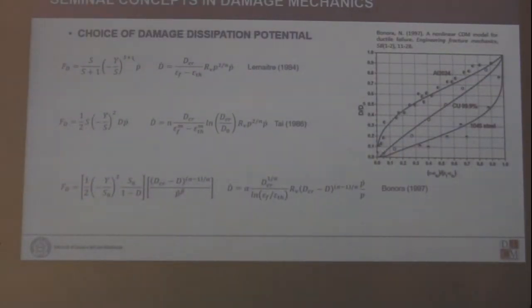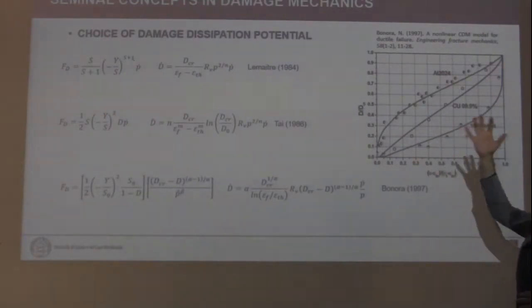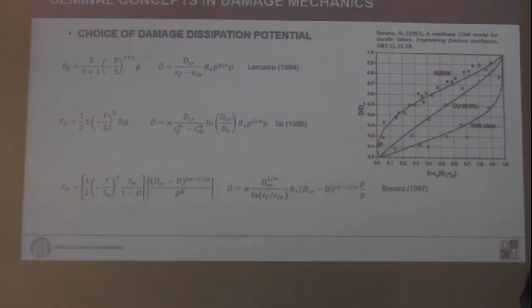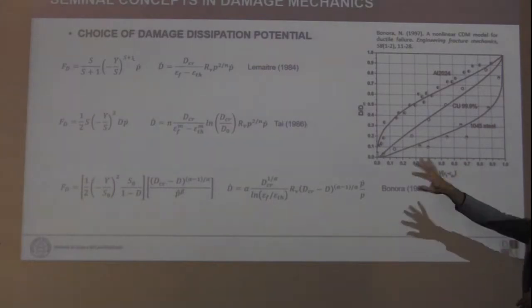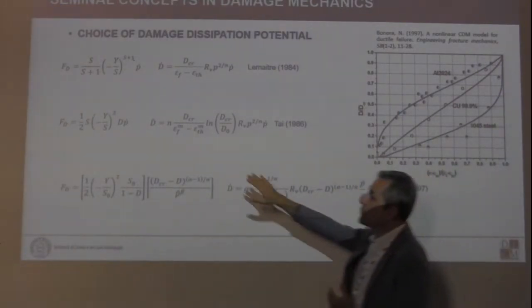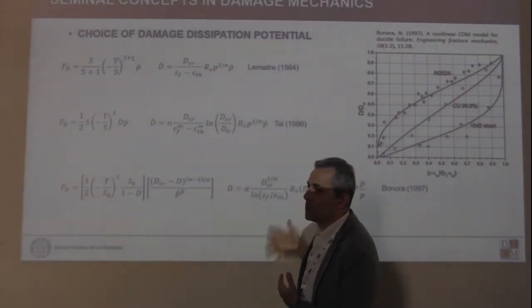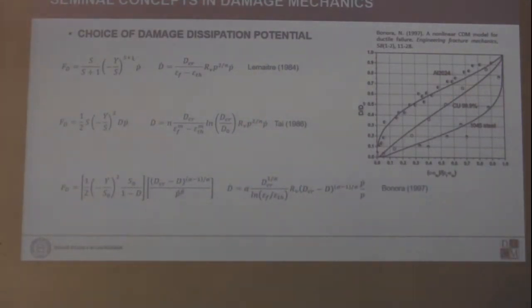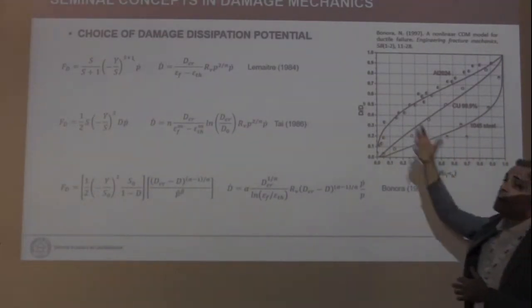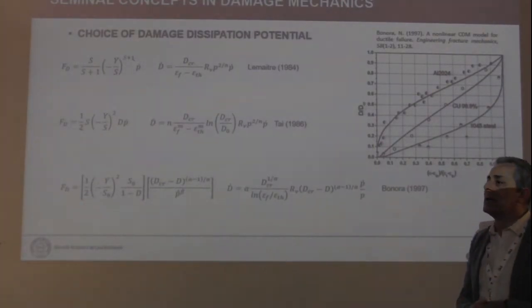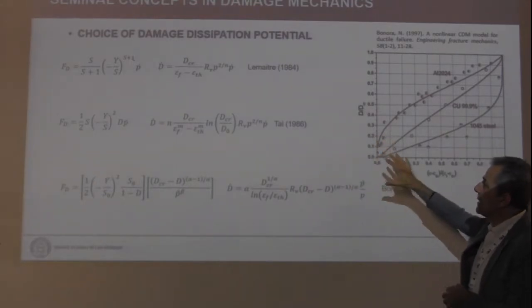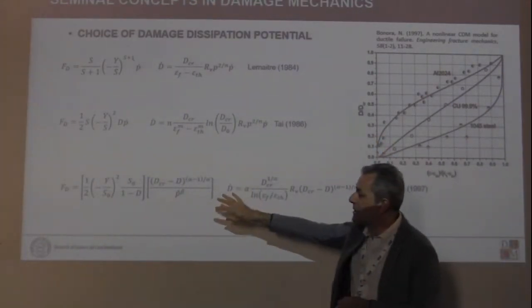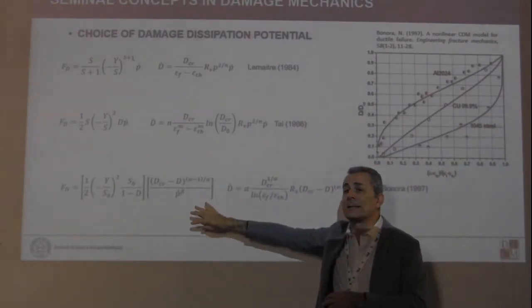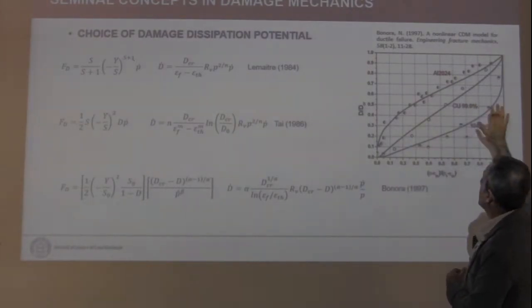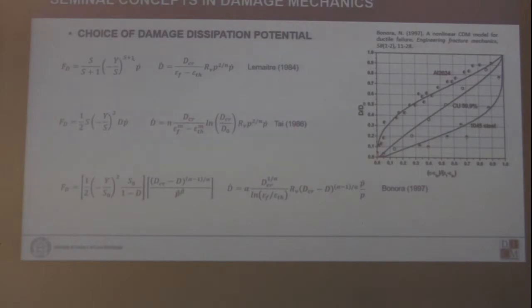Then the game goes in the choice of the damage dissipation potential. In the literature, a number of authors provided possible expressions for the damage potential. If you find an expression for your damage potential, then from this one you come up with the damage evolution law. So different damage evolution laws can be formulated. Some of them are very rough in describing the damage evolution in material, and again are not supported by experiments. At that time, I tried to find a damage dissipation potential that could account for the plastic strain history and be capable of describing different damage evolution in different classes of material, to be as general as possible.